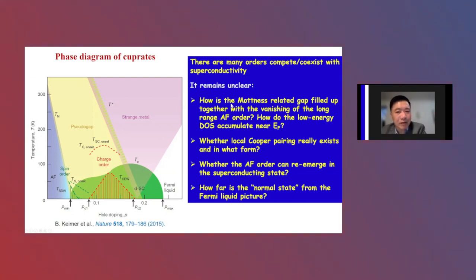For example, how is the Mott-Hubbard gap filled up together with the vanishing of the long-range antiferromagnetic order? And how does the low energy density of states accumulate near EF, the Fermi energy? This second part is very important, because in the correlated system, we don't know how the low energy density of states accumulates. We need some direct evidence for that, okay? And also whether the local Cooper pairing really exists and in what form, and whether the antiferromagnetic order can re-emerge in the superconducting state, if it is a competing order. And how far is the normal state from the Fermi liquid picture? So these are some very important topics I want to address today through our data, okay?